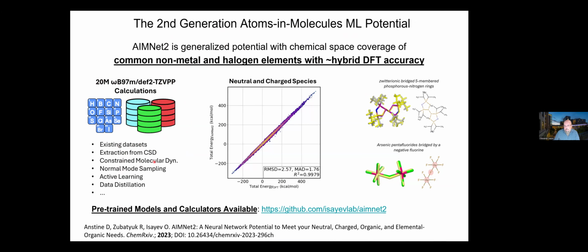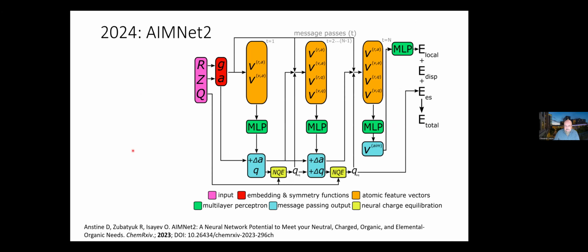Now, in contrast to the original neural network, it works for neutral and charged species. So you can encode the molecular charge and the spin states. In addition to organic molecules, it also works for elemental organic molecules, things like molecules with boron, silicon, selenium, and so forth. Now, if you're curious about the architecture, this is the architecture, and it's much more complex. In addition to being a purely geometrical descriptor, the network is now conditional on the total molecular charge and multiplicity if it's an open shell system. So you can describe radicals, spin states, and here I think you might have interest in that as well. Now, in the ANI architecture, our descriptor was purely derived from symmetry functions by hand.